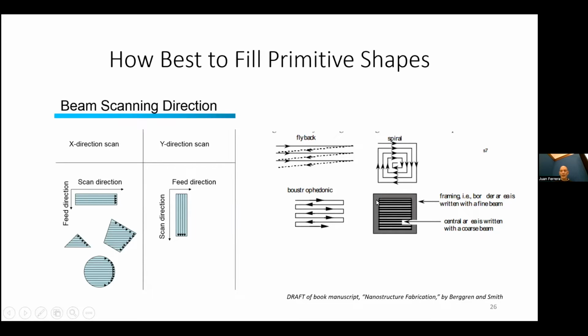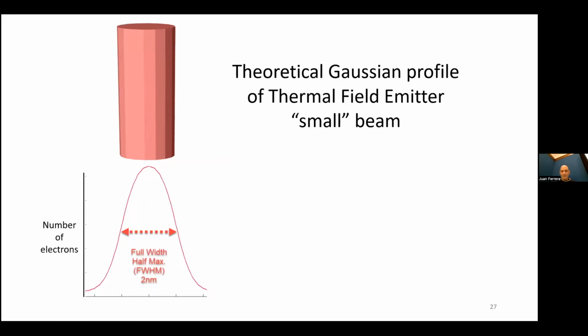Or you can do these other schemes, which you can implement whether or not your tool has different fill schemes by pre-preparing your pattern, is to write edges around with small beam current and then fill in the middle with a much larger beam current and still maintain nice edge roughness.